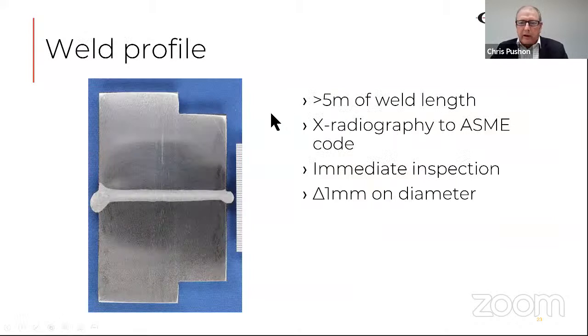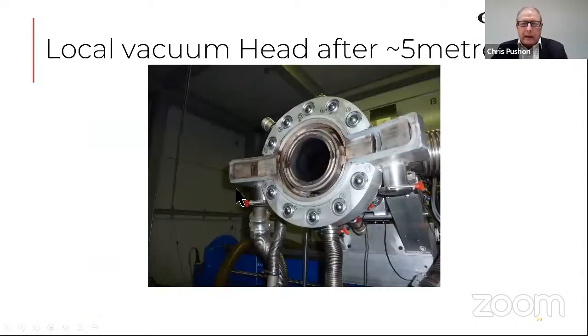We also radiographed the weld, and it was acceptable to the ASME code, no indications. And again, you can use immediate inspection. It's cold enough to inspect when you finish. This is a macro section through the weld, which shows the weld quality. And the fairly agricultural welding head. So this is a vacuum system, which doesn't really look like a vacuum system, but it's a consequence of the pressure that we work at.